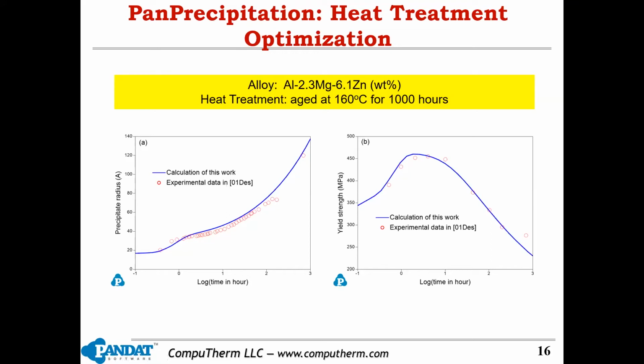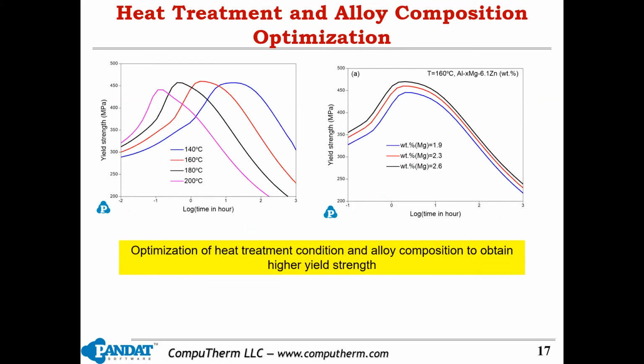With this type of calculation, simulation, we can perform virtual experiments. So in this slide, I show virtual experiments. We basically perform aging at 4 different temperatures. As you can see, at higher temperature, you can reach a peak yield strength very quickly. However, it's not the highest yield strength, right? And then you can use other temperatures.